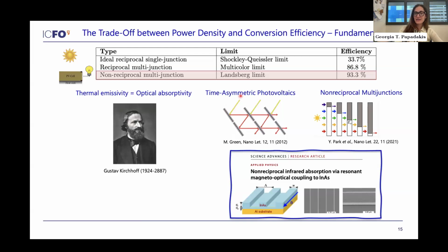In this case, a cell absorbs from one side, for example direct sunlight, but then the emission of the cell, because everything that has a non-zero temperature emits, is directed towards another cell. And in this case, Martin Green showed here that indeed I can recover the Landsberg limit. Of course, it's far easier to do this in transmission mode. So this is a more recent paper that shows a similar concept, where by enabling non-reciprocity in materials, I can get the Landsberg limit.